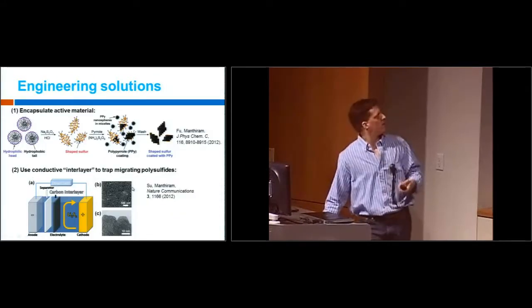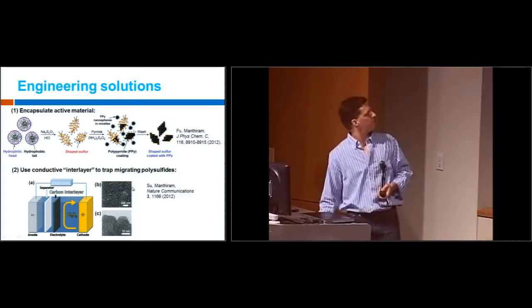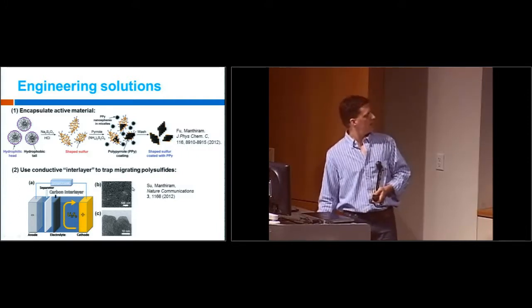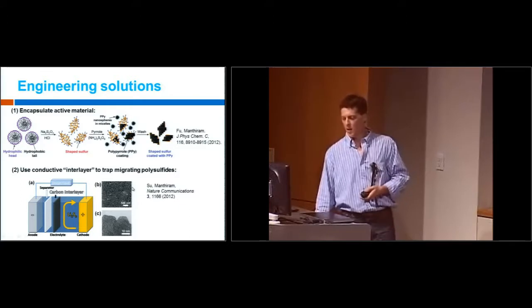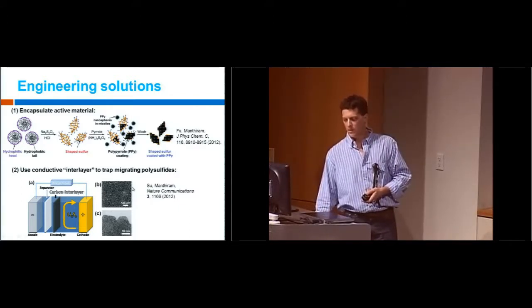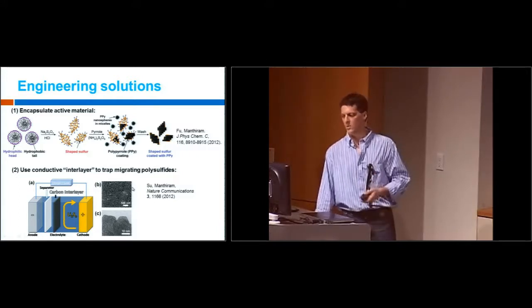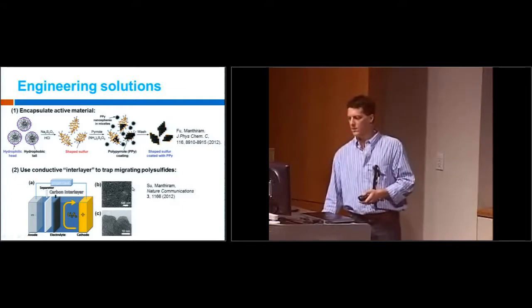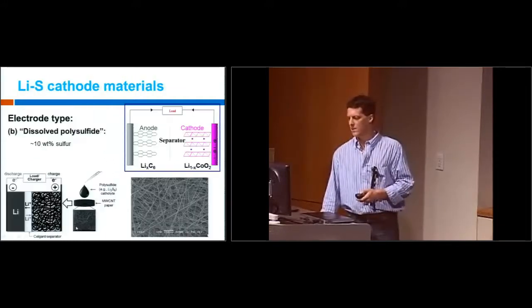To improve this, and this is work from our lab, there's a lot of similar work in other labs, people take different ways of encapsulating the sulfur, in this case with a conducting polymer, and you just try to wrap it up as best you can. The other thing that's been done is to take another layer of carbon and insert that between the cathode and the anode, so that when the material begins dissolving, it can get trapped in between the layers. And these have helped performance to a certain degree for the slurry-based cathodes.